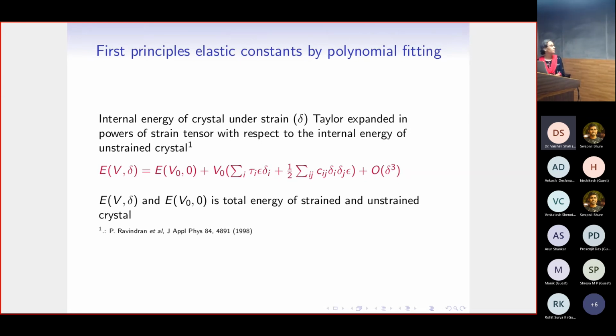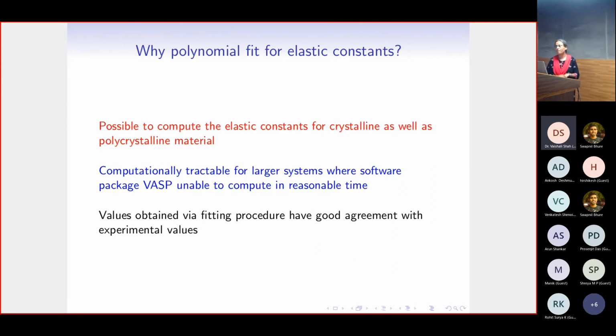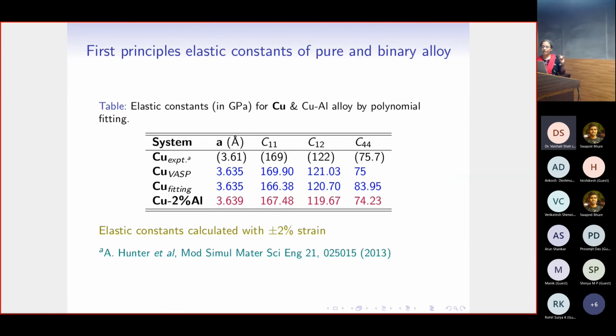So we validated this methodology. Why we chose this is because we want this in a reasonable amount of time. We can do this for crystalline as well as polycrystalline materials, and we found that this methodology gave us good agreement with the experiment. So I'm putting in the data that we have obtained for the work I've been doing with Guru related with the copper aluminum system, and this is the one on which we actually did the first test. So this is basically the elastic constant that we have obtained from the module that is inbuilt in the software. And fitting means we follow the polynomial fitting method that I described just now.